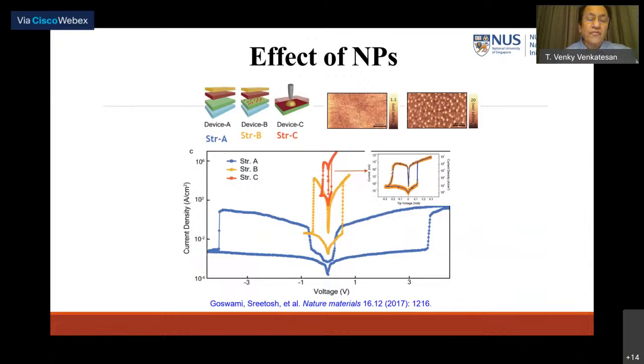Now, I go to even further field enhancement, where I replace the top electrode with a conducting AFM tip. Now the device is roughly 60 nanometers squared in area. And for this device, the switching voltage drops down to 110 millivolts, and the current density goes to megamp per centimeter squared. So the field enhancement really helps this device. And in fact, when you make the device smaller and smaller, it gets better.